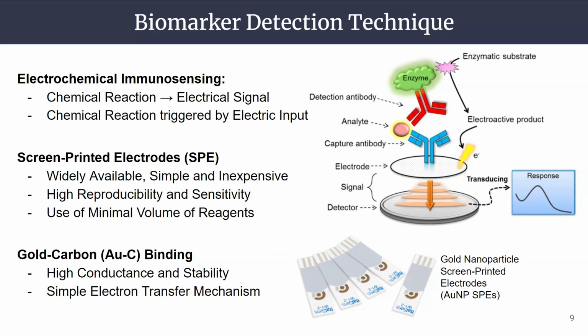This technique can be miniaturized by using screen-printed electrodes. They are widely available and allow for a simple and inexpensive detection with high reproducibility and sensitivity and minimal use of reagents. One of the most important parts of the detection is the immobilization of the capture antibody over the transducing platform, which in this case is the working electrode of the screen-printed electrode. And a gold-carbon binding approach for antibody immobilization has shown a high conductance and stability in a simple electron transfer mechanism, increasing the sensitivity of the developed sensor.